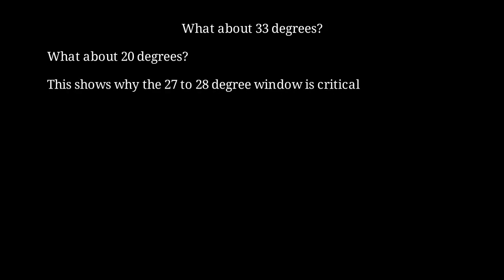What about cooling directly to 20 degrees? This would create huge supercooling for all crystal forms. You'd get rapid nucleation of forms 1, 2, and 3 simultaneously. The chocolate would solidify quickly but in the wrong forms, giving poor texture and bloom susceptibility. This shows why the 27 to 28 degree window is so critical. Too hot and Form 5 won't nucleate. Too cold and the wrong forms dominate. The process requires precision within about 1 to 2 degrees.